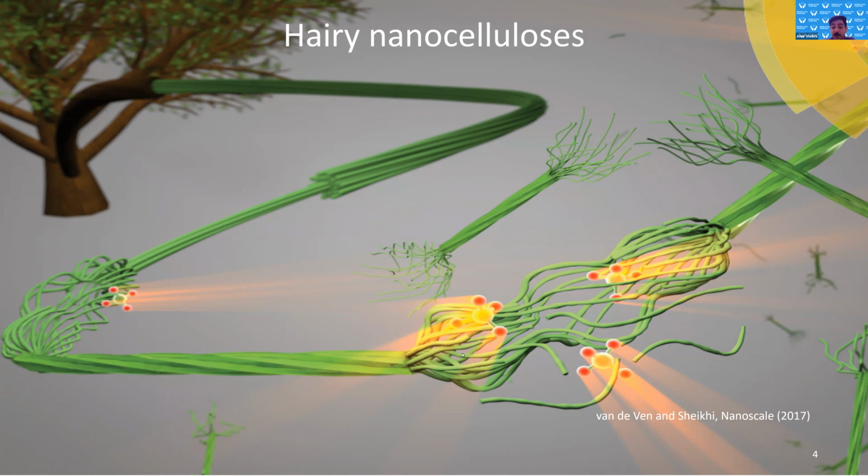So what we do is to preferentially oxidize the amorphous regions using periodate and chlorite oxidation and disintegrate the cellulose fibers from the amorphous regions to cellulose nanocrystals sandwiched between two layers of highly functionalized celluloses. And we have been engineering these cellulose nanocrystals for a broad range of applications, some of which I'm going to explain today.